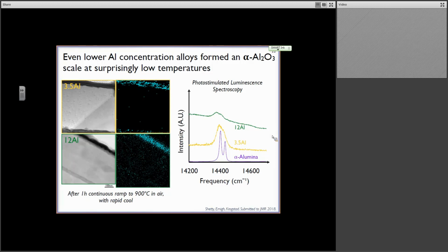We can see that by this photostimulated luminescence spectroscopy over here. The purple one here is a reference of actual sapphire. For both the low aluminum and the high aluminum, we have this characteristic doublet that is not seen in any of the other polymorphs. This was actually quite surprising because typically we expected to get aluminum oxide here, but not at the temperatures that we went to. We only went to 900 C. Oftentimes, we only find the alpha phase of alumina forming above 1,000 degrees C.